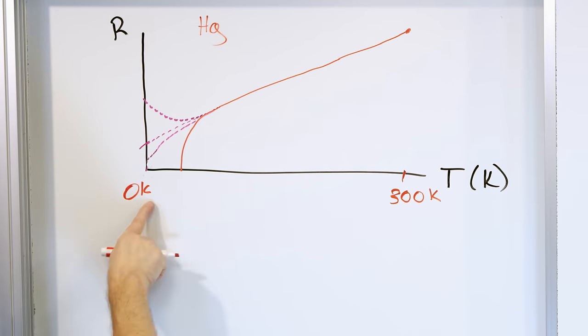of 250 Kelvin. Look at this. Room temperature is just under 300 Kelvin. So 250 Kelvin is really close to room temperature. But there is a catch. The only way they were able to get 250 Kelvin is by applying pressure to this thing. And not just a little pressure, 170 gigapascals.